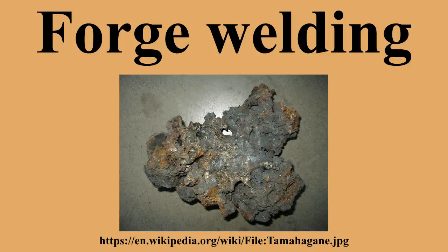Flux. Forge welding requires the weld surfaces to be extremely clean, or the metal will not join properly, if at all. Oxides tend to form on the surface, while impurities like phosphorus and sulfur tend to migrate to the surface. Often a flux is used to keep the welding surfaces from oxidizing, which would produce a poor quality weld, and to extract other impurities from the metal. The flux mixes with the oxides that form and lowers the melting temperature and the viscosity of the oxides. This enables the oxides to flow out of the joint when the two pieces are beaten together.